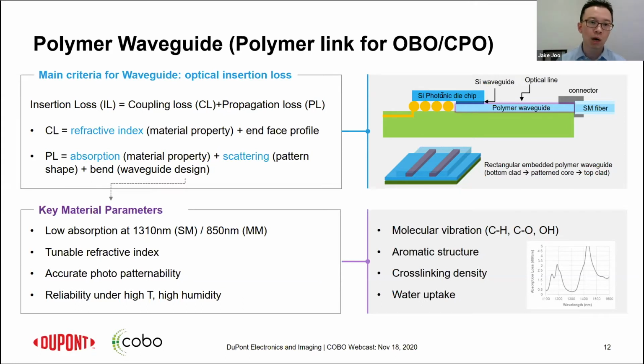Insertion loss is comprised of coupling loss, which goes between a fiber to waveguide or waveguide to waveguide. That is defined by the refractive index difference between fiber glass to air to waveguide, or index matching fluid, as well as end face profile. You also have a propagation loss. That is really a core material property. If the material absorbs at single mode waveguide 1310 nanometers, at high absorption wavelengths, then that will end up being a high loss.